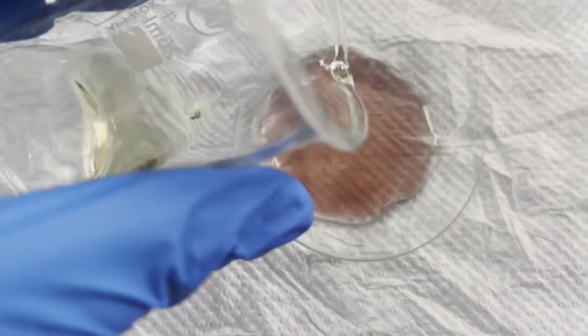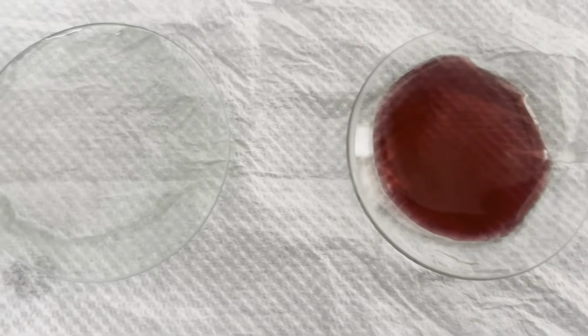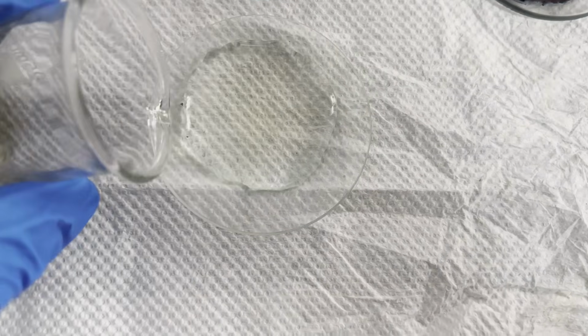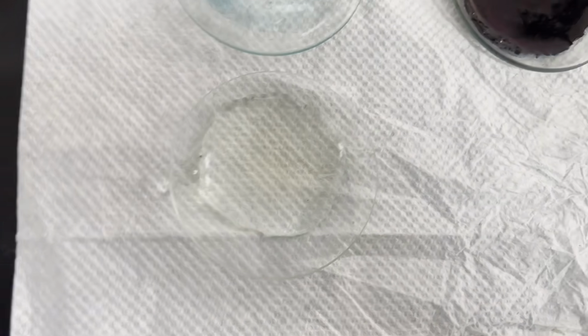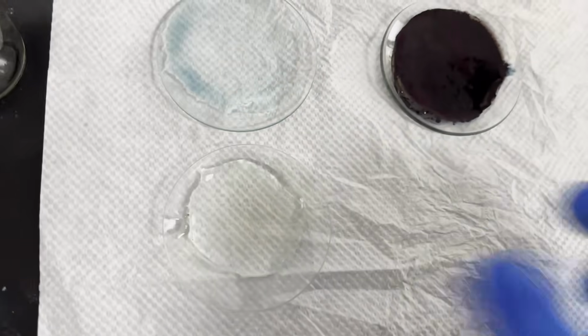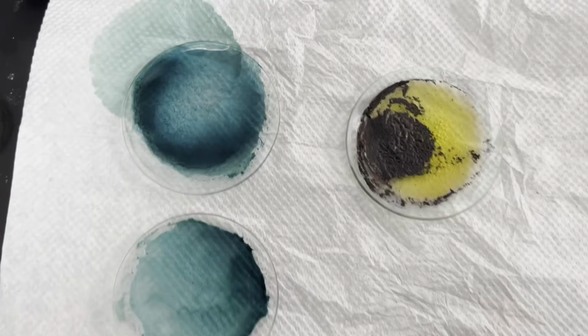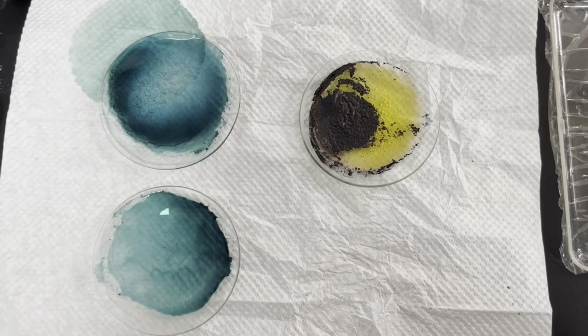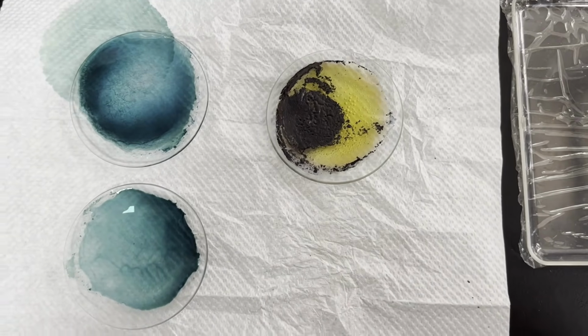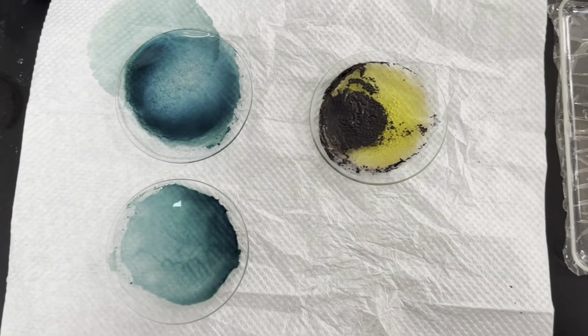As a control, a solution of around 20% sodium chlorate immediately turned red and then black. After 5 minutes, a blue color developed in the electrolyte, and another control was done using a 1 gram per liter potassium chlorate solution, where a tiny tint of blue is produced. 2 hours later, both turned to a similar blue color, showing that the amount of chlorate in my electrolyte is close to 1 gram per liter.